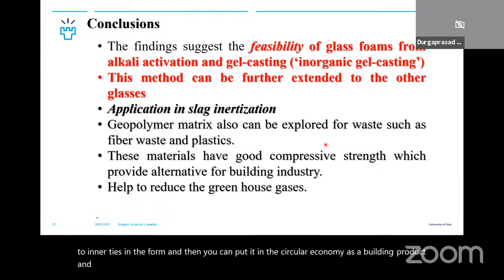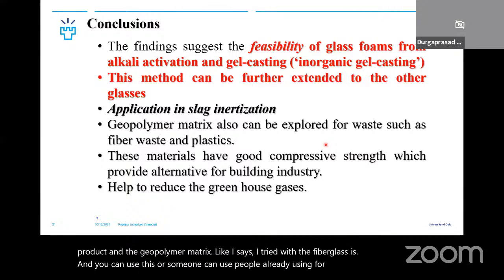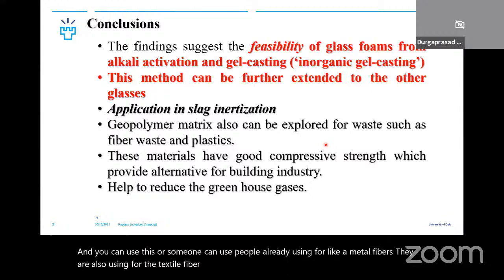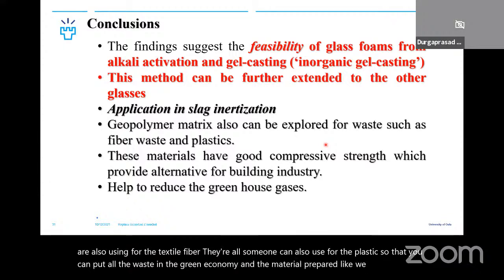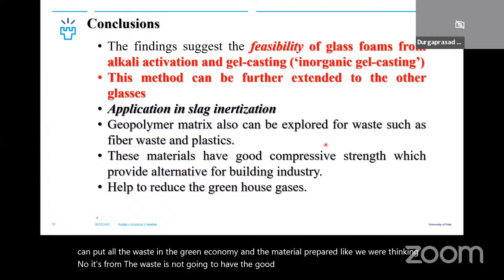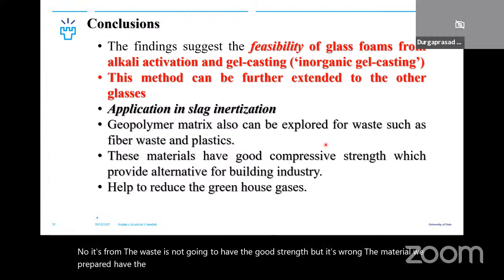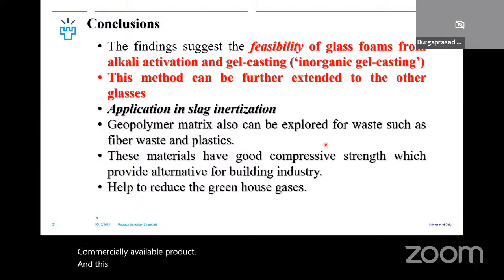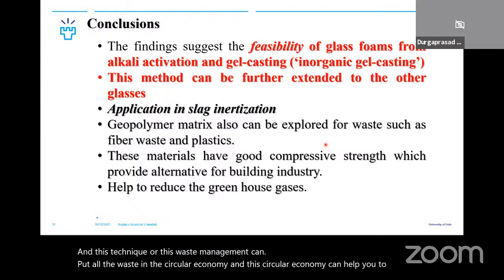And the geopolymer matrix, like I said, I tried with the fiber glasses. And people are already using it for metal fibers. They are also using it for textile fibers. Someone can also use it for plastic, so that you can put all the waste in the green economy. And the material we prepared, we were thinking it's from waste, it's not going to have good strength, but it's strong. The material we prepared has good strength, comparable with the commercially available product. And this technique or this waste management can put all the waste in the circular economy, and this circular economy can help you to reduce greenhouse gases.